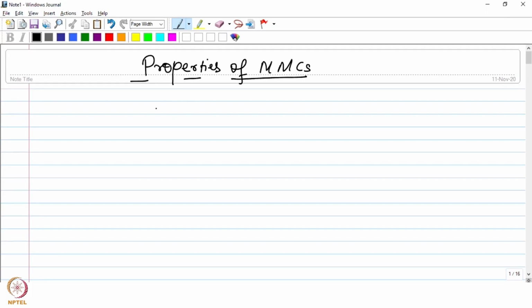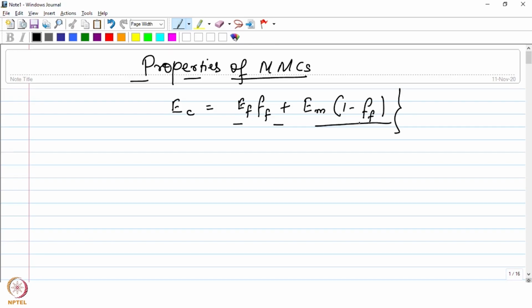And with regard to the property of any composite, we have seen that it can be obtained from the rule of mixture, by the weighted average of the properties of the individual constituents. So for example, if you talk about a fiber reinforced composite, the elastic modulus of the composite EC can be obtained as this, where FF is the volume fraction of the fibers.